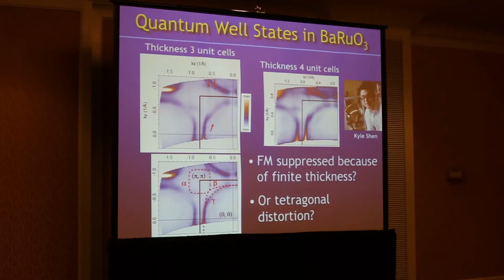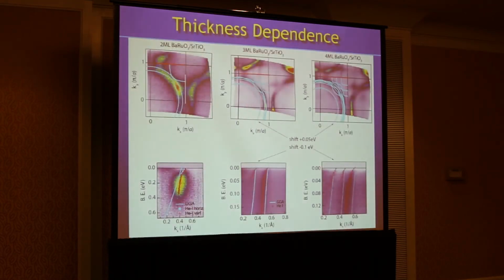Okay. So here you can see, looking at these as a function of thickness, that they seem like they agree fairly well in terms of the Fermi surface with these first principles calculations. But then when you look at the energy cuts, you can see how they disagree quite a lot. So if we want to make progress in better understanding and having better theories for these correlated systems, I think it's imperative to not only be able to calculate electronic structure, but be able to compare it to electronic structure on those same materials.